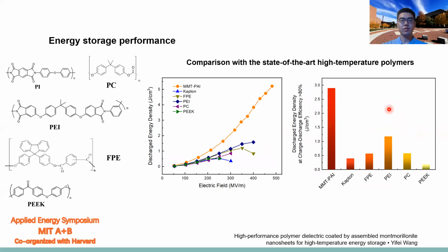And we compared the energy storage performance of these materials, the coated PAI, with some state-of-the-art high-temperature polymers. We can find that our material shows the highest discharge energy density at 150 degrees C at the same electric field. We can also extract the energy density at efficiency higher than 80%. We can see that this MMT-coated polymer, the PAI, shows outstanding performance when compared with these high temperature polymers.